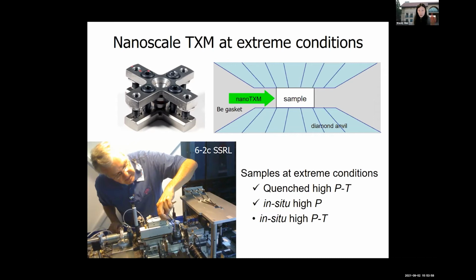Here we used a modified diamond cell for that purpose, because if we want to do tomography, then we need to have as much side access as possible. 180 degrees would be ideal, because that would give you complete access. But with the pins in our diamond cell, for this cross cell we're limited to about 160 to 165 degrees access. So we have about 15 to 20 degrees of missing angle. Then we direct our X-ray beam perpendicular to the diamond axis, and we use an X-ray transparent gasket like beryllium.